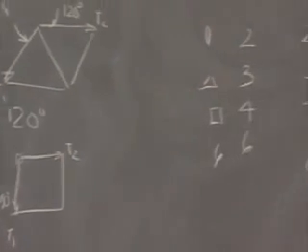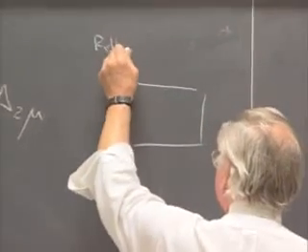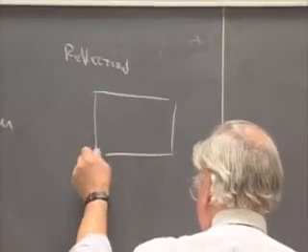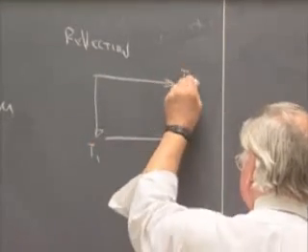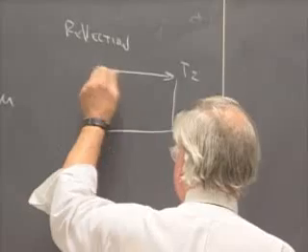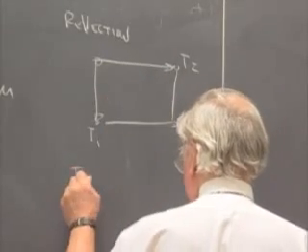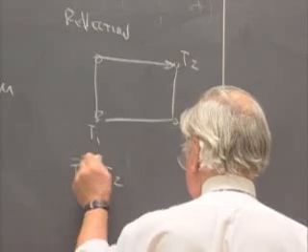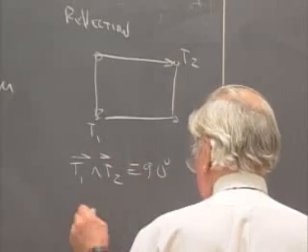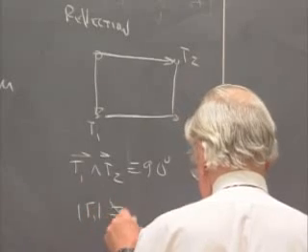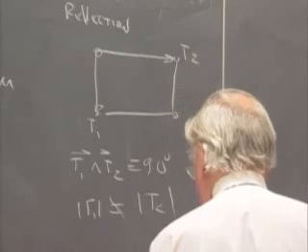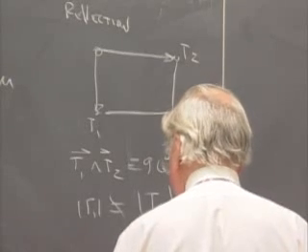And then the place at which I'm going to pick up today in just a moment is the case of a mirror plane. And reflection we saw, depending on how we arrange the translations relative to the reflection plane, could give us either a lattice in the shape of a rectangle, and here T1 and T2 made an angle of exactly 90 degrees, but the magnitude of T1 could be anything it liked relative to the magnitude of T2. And then a double cell, which had the shape of a diamond,